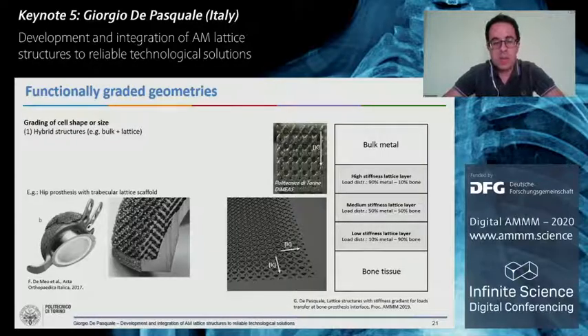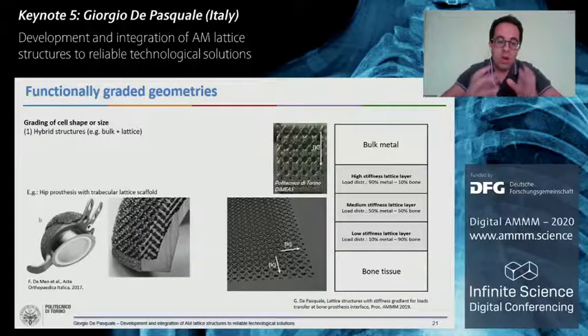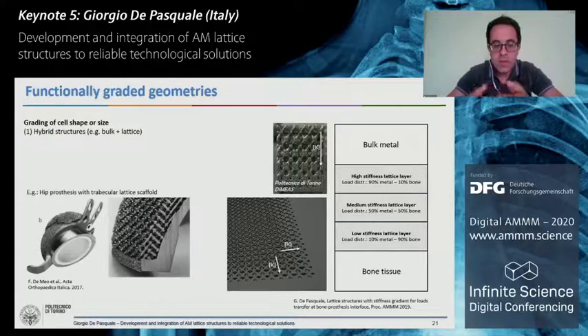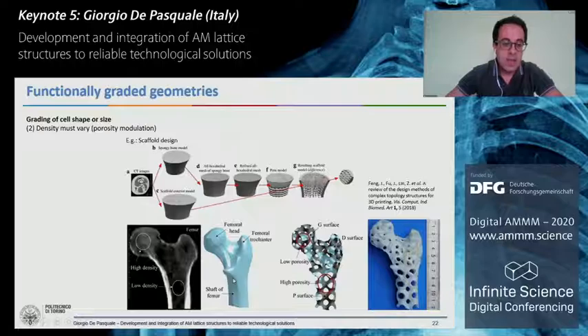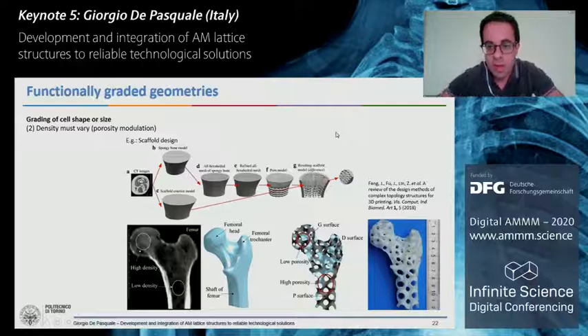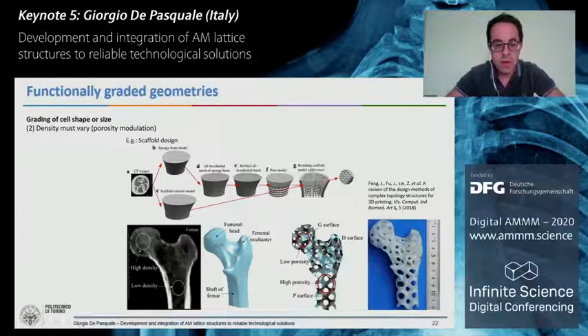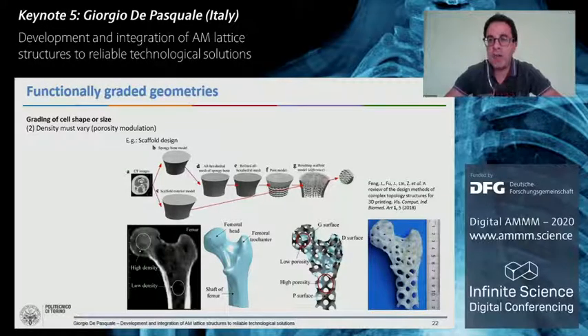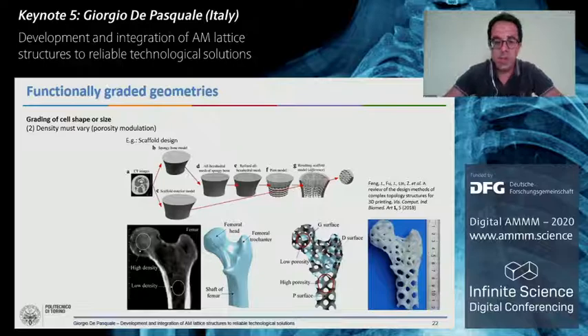For example, in the coatings of prostheses, it is quite useful to improve the adhesion between bone tissues and to have a gradual variation of stiffness that allows the bone to train itself for improving the anchoring. The same thing is also used in literature for reproducing biological tissues where the density is variable. For example, in a femur with a CT image, you can understand where the density is high and low, and reproduce the same by using different densities of the lattice structure.